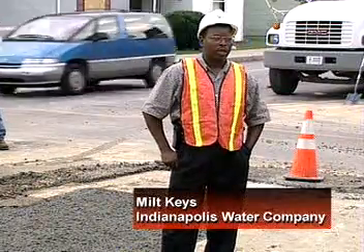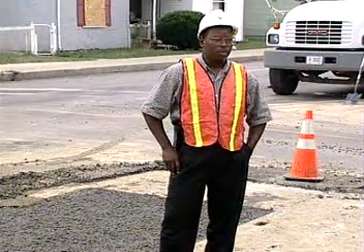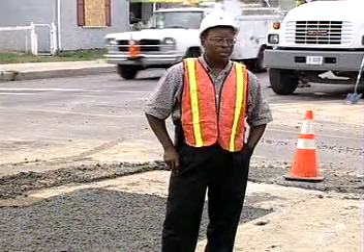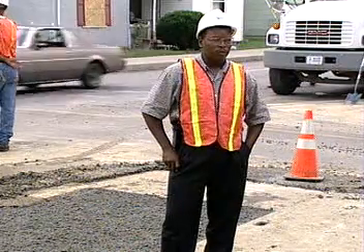Ever since 1990, we've been watching, and we've never had to go back on one that had flowable backfill in it. In the past, we would make an excavation, backfill it with the granular material, finish our cap, then we would come back 30 days later to inspect that trench to make sure it was not settling. We found that we were going back 60% of the time to restore a trench that had failed. By using flowable fill, we reduced that return time to 0.